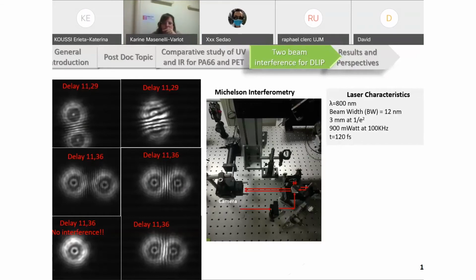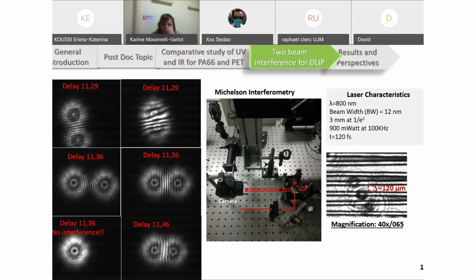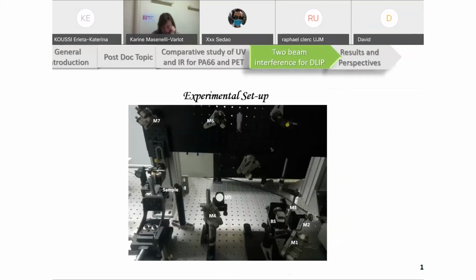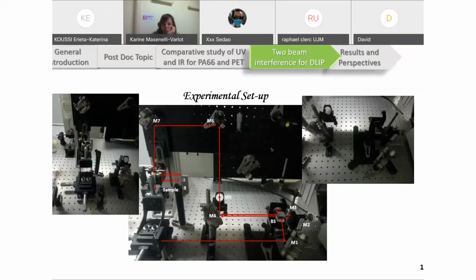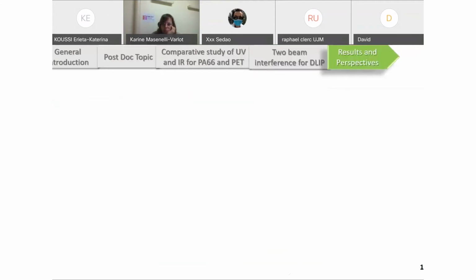The period was roughly measured at 120 micrometers. So after the observation of the fringes, we have now implemented the sample. Before it we have an objective lens with a magnification of 40. The sample under study for the preliminary test is a silicon sample. And here is the zoom of the beam splitter and the sample placed on the translation stage.